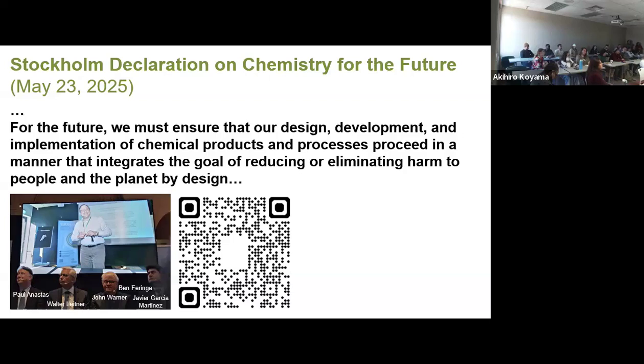There is a lot of progress in this area. Cellulose-based foams that are water resistant that you can use in immersion conditions in water. This is possible. And all it is is that you bind the materials together so strongly that water cannot go in. So the short answer is, you do develop water resistance if you play with these concepts. It's possible. But pure cellulose will be hygroscopic. That foam that I showed, if I put it outside, it will absorb water and the properties will change, right? Definitely. But you can go against that by doing chemical modification.